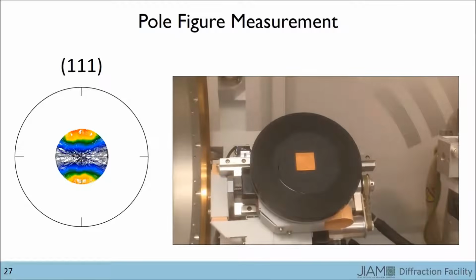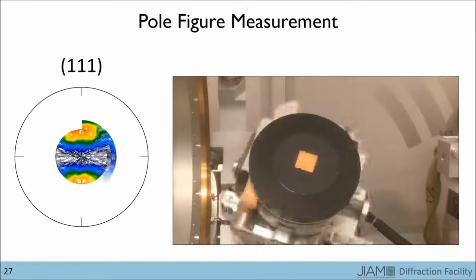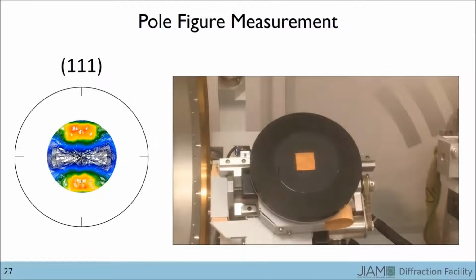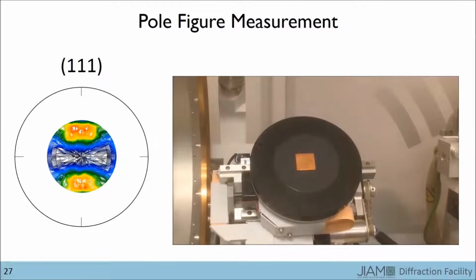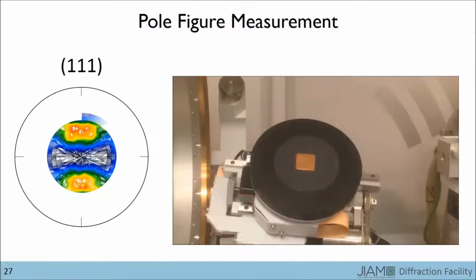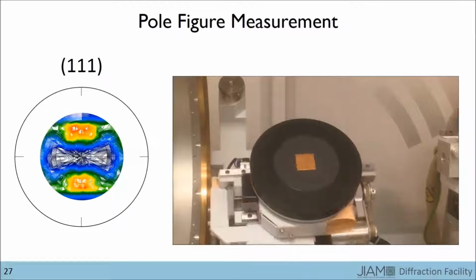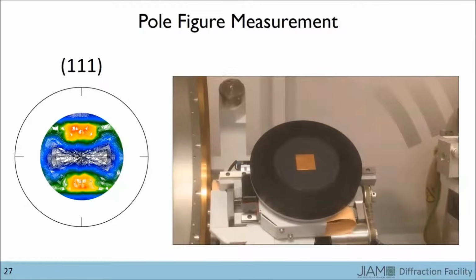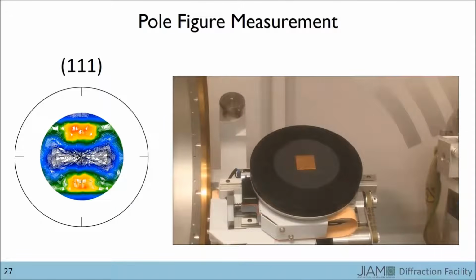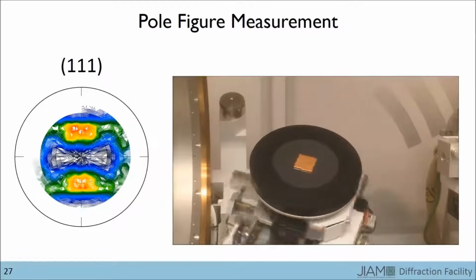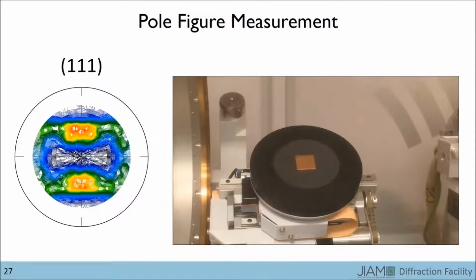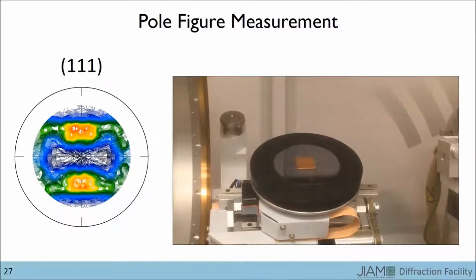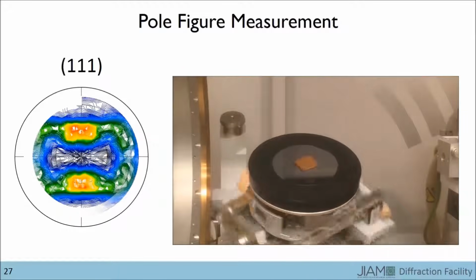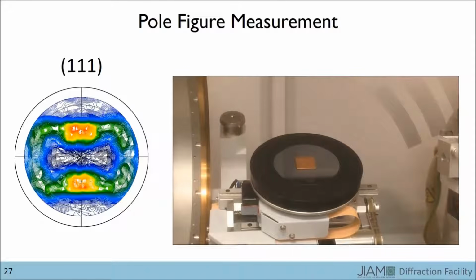As we continue to rotate further in chi, more intensity is seen at certain parts of the plot. We continue this until chi reaches approximately 70 to 80 degrees, because it is at this point that the X-ray beam typically begins to fall off of the sample. Because this type of experiment deals strictly with the intensity of the peak, the entire X-ray beam must remain on the sample throughout the experiment. We see that at certain orientations the intensity is much stronger. This tells us how the 111 planes are preferentially oriented in our sample.